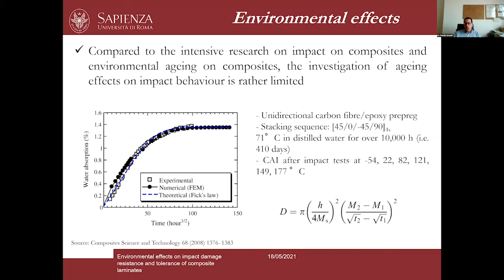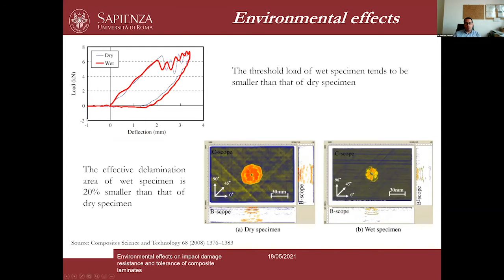So pretty low. The problem is that despite this very low water absorption, here you can see the impact response curves for dry and wet specimens. And again, despite the pretty low water absorption, you can see that there is, for example, an effect on the impact response curves. In this specific case, the threshold load of the wet specimen was significantly reduced compared to the dry specimen. And a much more important issue here is the extension of the delaminated area.